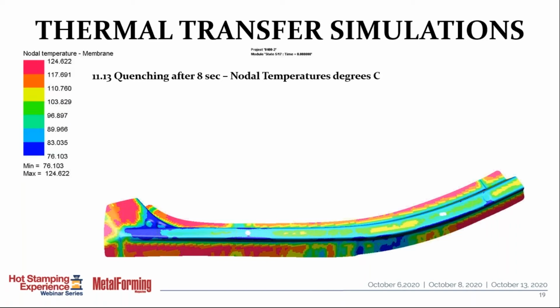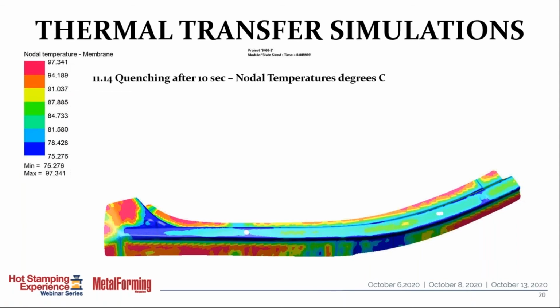If we're not quenching fast enough, we have to do something better with the cooling in the tool in order to accomplish that. Or we may have to increase the quench tonnage to accomplish that. Ideally, you quench with as little force as possible and as quickly as possible. That gives you the best possible die condition where you're not picking up any aluminum silicon residues into the tool that reduces the frequency of cleaning.